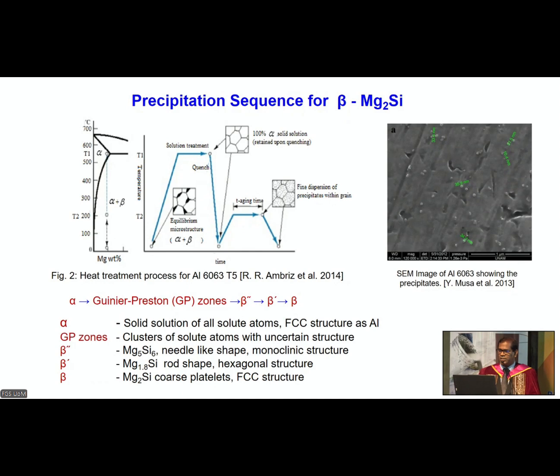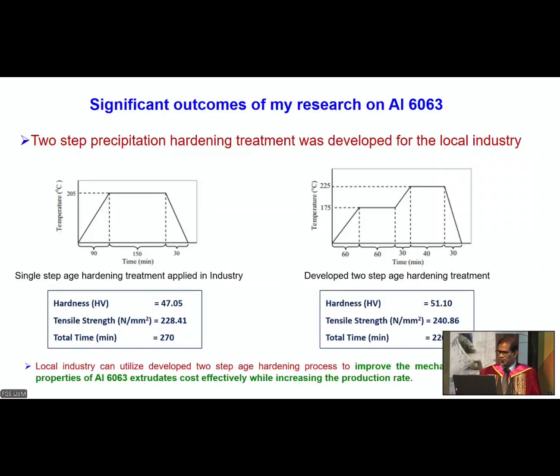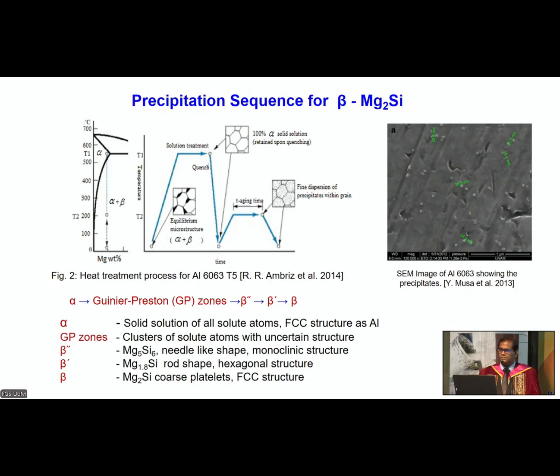And here you can see in this same image how the precipitates, actually magnesium silicide precipitates with a size of around 30 to 40 nanometers, are distributed in the matrix. These particles, as I explained, are the precipitates making a barrier for dislocation movement and giving the strengthening effect.